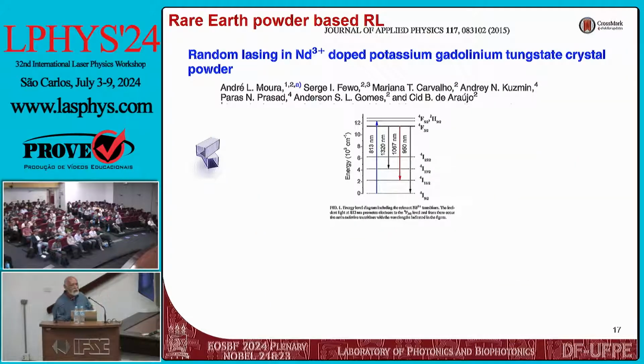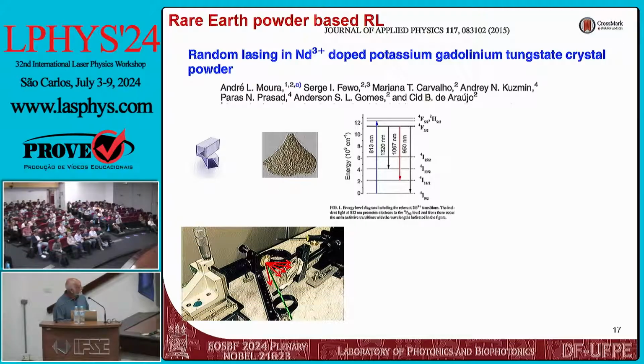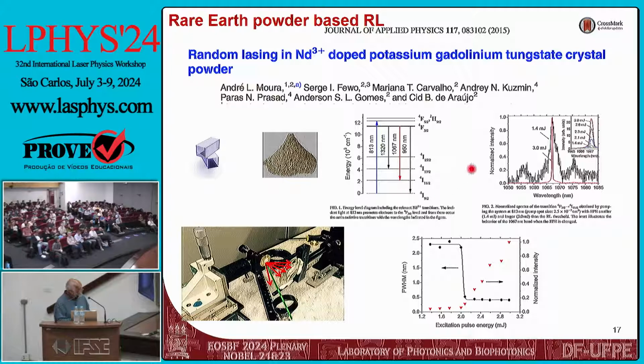For instance, if you take a crystal, neodymium, in any kind of host, a medium appropriate for lasing, if you crush it into a powder, neodymium has those levels. You look at the 1 micron, well-known emission. Here you see the spectrum, a wide spectrum below threshold, and then a very thin spectrum above threshold. And here is the measurement. We see this typical signature, which is enough to show that we are lasing, but now and again, we also do the measurement for coherence and so on and so forth.